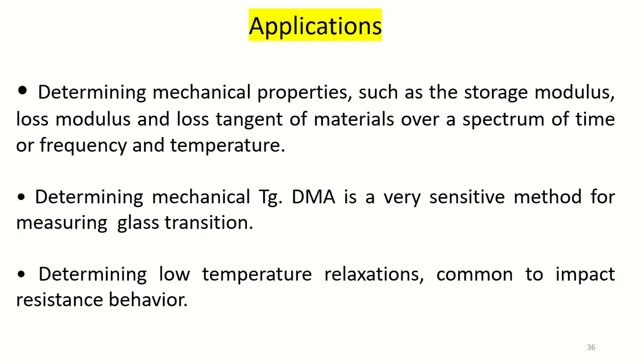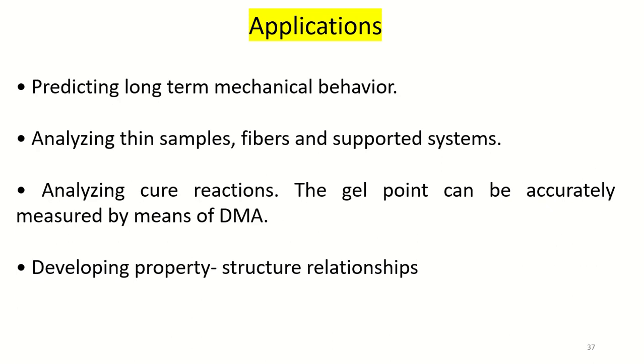The third is determining low temperature relaxations common to impact resistance behavior. The fourth one is predicting long term mechanical behavior. The fifth one is analyzing thin samples, fibers, and supported systems. The high sensitivity of dynamic mechanical analysis for measuring stress and strain means that one can analyze samples where very small forces are involved. This is the case of fibers and films.